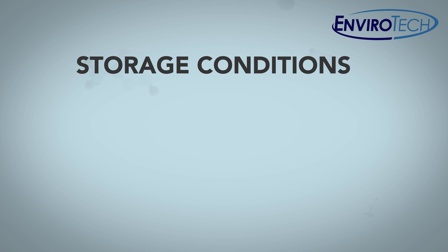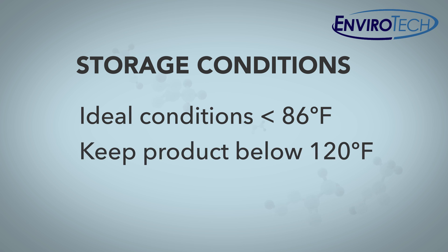In order to maintain the guaranteed one year shelf life, PAA containers should be stored in warehouse conditions below 86 degrees Fahrenheit. While this may not always be possible, it is imperative that the bulk liquid does not exceed temperatures of 120 degrees Fahrenheit. Furthermore, it is recommended that PAA products be stored indoors and out of direct sunlight to prevent premature degradation.